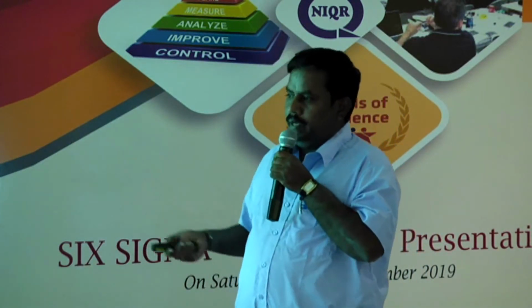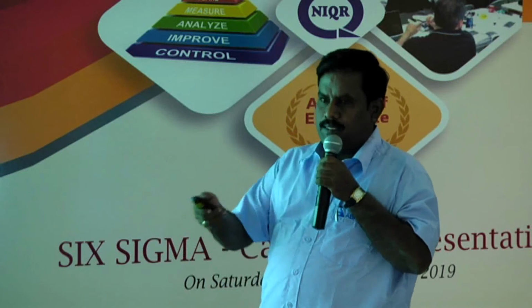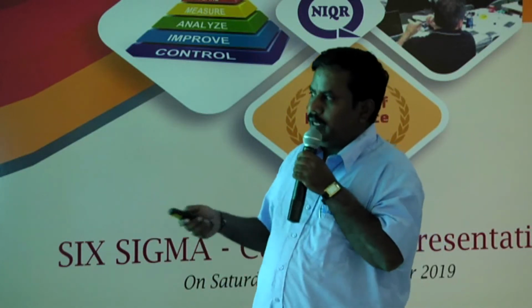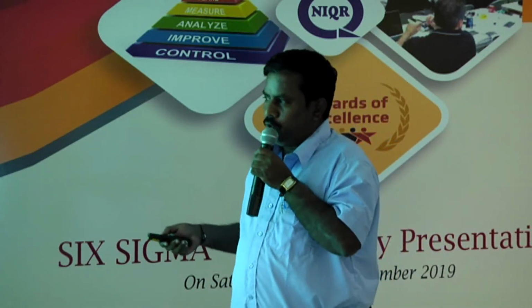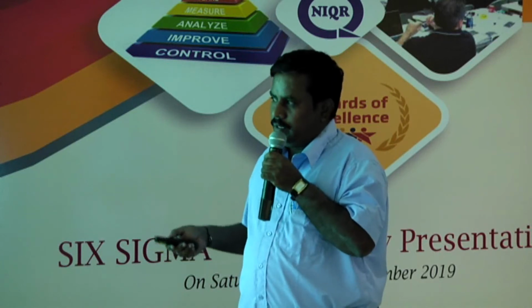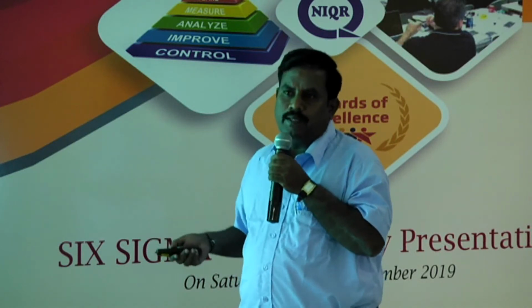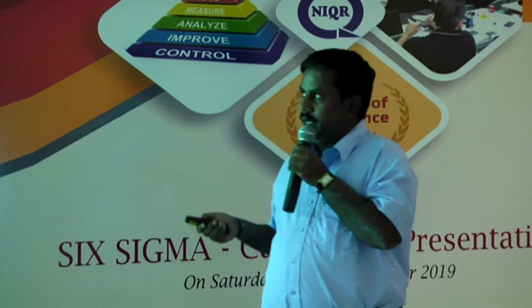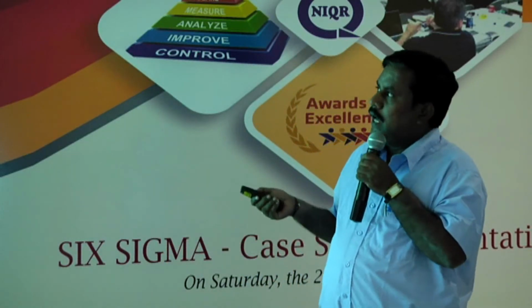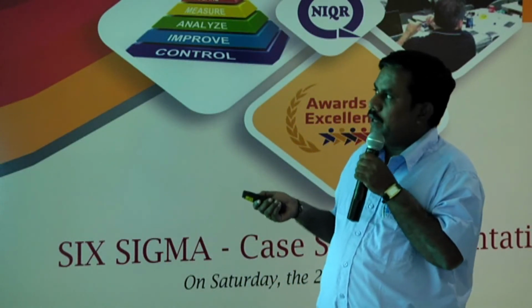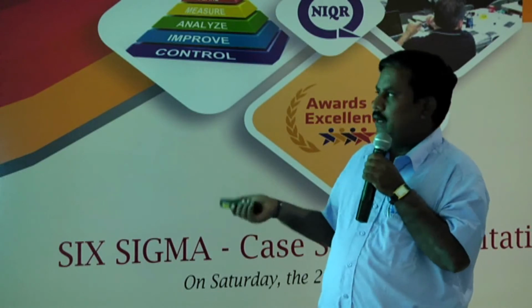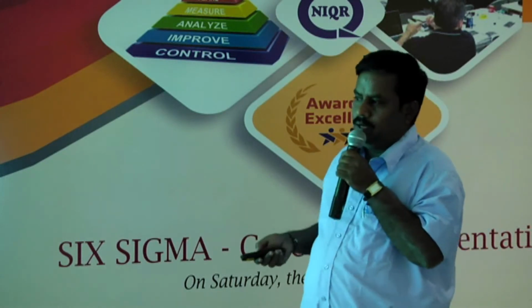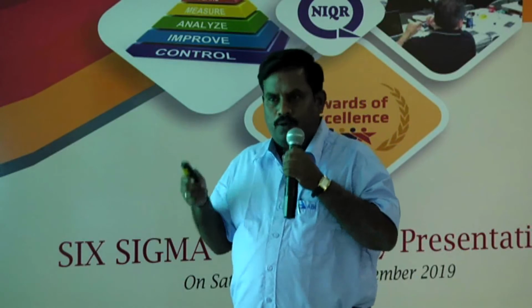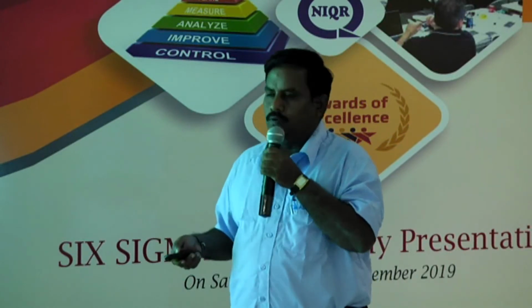Then to maintain die temperature, the die thickness is high. For that we moved to the tool room and took a riser back wall to reduce the die thickness size. The technical background of this improvement is, if die thickness is reduced, the temperature is maintained uniformly on the die surface. This will keep the die temperature uniform on the shop floor.